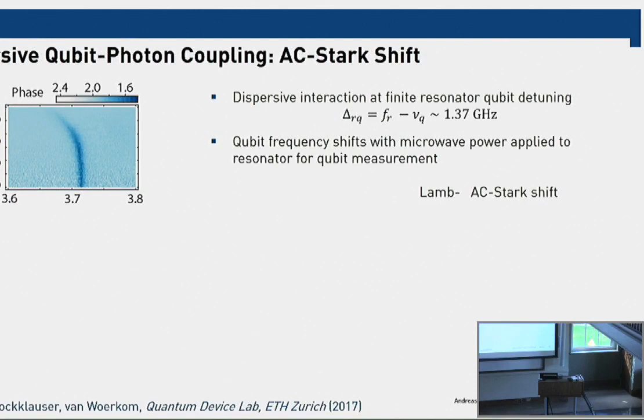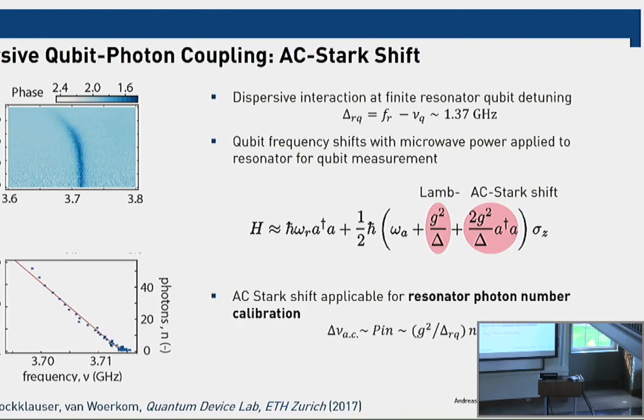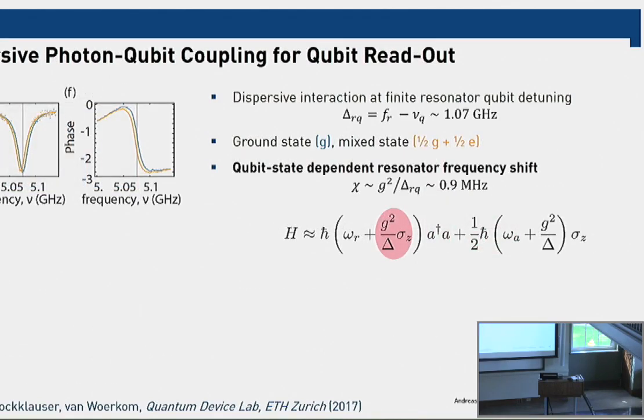So then you can do all the other cavity QED stuff. You could look at qubit photon coupling and measure the AC Stark shift. And if you measure the AC Stark shift, you can calibrate the photon number inside the resonator. So you can calibrate your external field relative to the applied external field and express that in terms of number of photons inside the cavity. And if you see the AC Stark shift, you also know that you should be able to do a good measurement, or you can calibrate a measurement of the quantum dot charge states that could be time resolved. And that's then something that we tried.